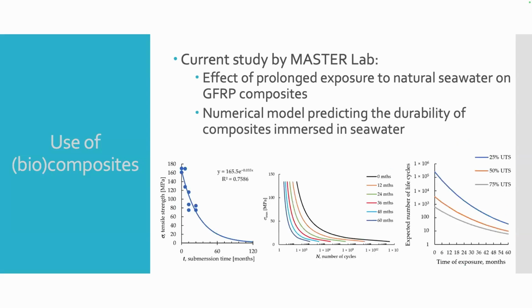We used these experimental results to do a regression analysis to predict how well they will behave in the future for an even more prolonged period of exposure. And what we of course know is that when there is a drop in the values of tensile strength, there is also a danger for the remaining fatigue life. So the SN curves also need to be adjusted according to the findings that we have.